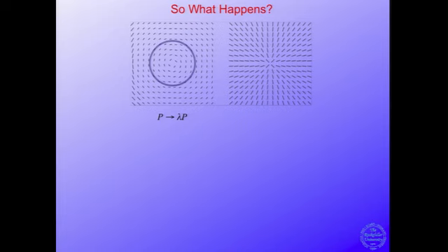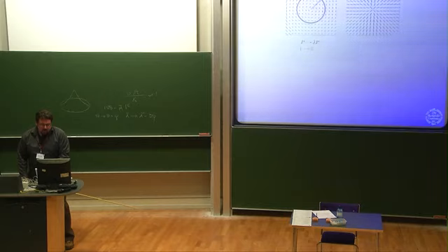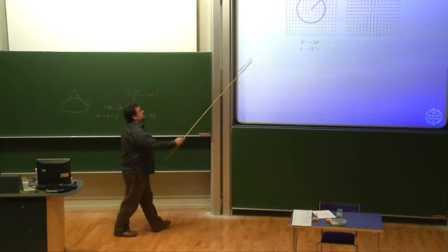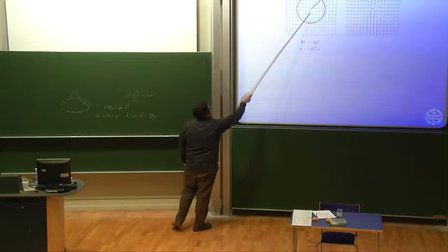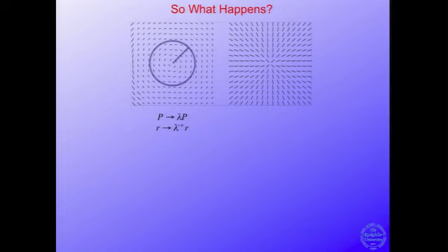Okay, so what happens? Let's start on the left with the azimuthal case. Let's imagine that we're going to heat the system. The order parameter is being lowered, so the system wants to shrink along the direction of the director field, and it wants to extend by some spontaneous Poisson ratio in the normal directions. If you look at an integral curve that lies tangent to the director field, it's the perimeter of some circle in a +1, and you get some deformation, lambda, which will be less than 1 for a heated system. So the perimeter wants to shrink. At the same time, by the Poisson ratio, you will get the opposite sense normal to the directors, so you get an extension of the radius.